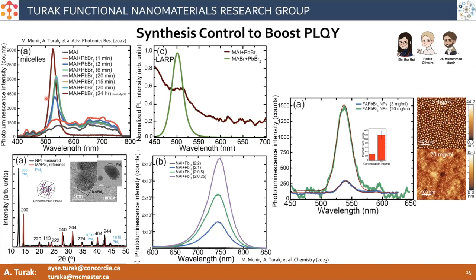And just by increasing the density of those particles, I have here an example of quite well-separated nanoparticles versus a quite densely packed array on the bottom. You can almost not see that they're nanoparticles. And this, again, leads to a six-fold increase in the emission under the same illumination condition. Right? So you can actually tune the quantum yield just by changing very, very simple synthesis parameters.